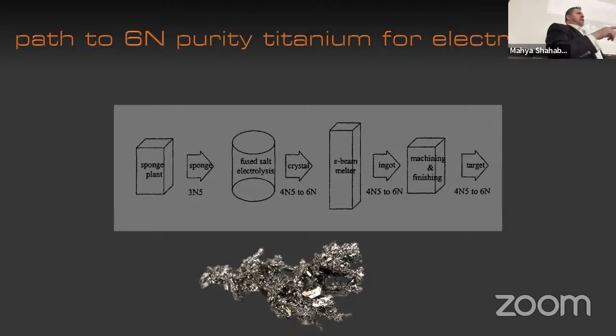Then we take that crystal and move it into a process that your fearless leader here knows all too well, the e-beam melting of titanium, which produces ingots out the bottom. We're not getting much purification in this step; usually, quality in is quality out, maybe a little bit of refining. And then the machining and finishing is basically taking an ingot about the size of floor to ceiling here and slicing it like a piece of salami. You're just making targets. You do a little bit of rolling just to get texture so that the sputtering works the way we want. But pretty much that's the end-to-end process from raw materials to the product sold into the